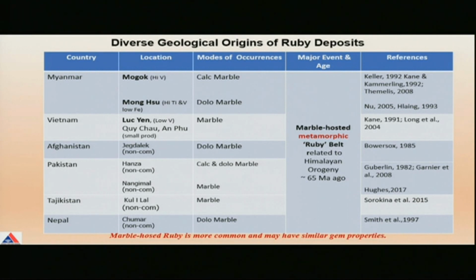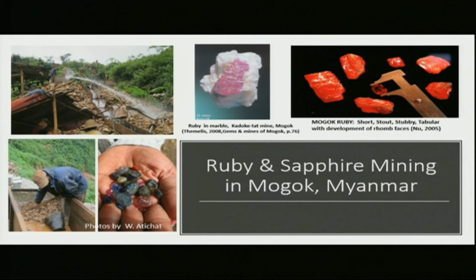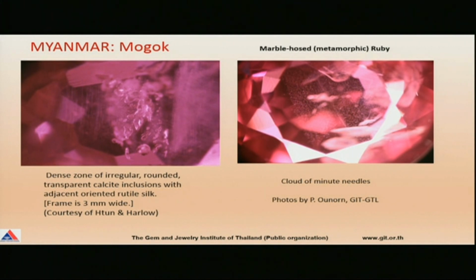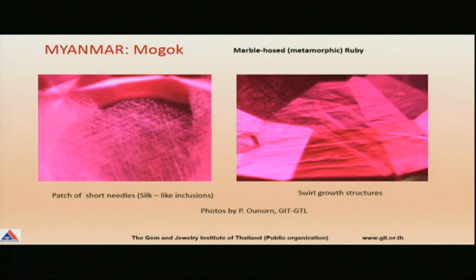You can see Mogok was associated with very coarse-grained calcite marble. And Mong Hsu is a little more toward dolomitic type marble and fine grain. And Luc Yen is also a medium-grain marble. Okay, the rest are similar, also hosted in marble, and also related to the Himalayan orogeny. This is an example of the ruby from Mogok. The diagnostic or locally specific inclusion features are transparent calcite inclusions, maybe somewhat rounded, irregular, and also rutile silk, very patchy type, and also a cloud of minute needles. And also short needle-like inclusions in a patch-like form. And an important one is also swirl growth structures, which are a good indication of a Mogok type ruby.